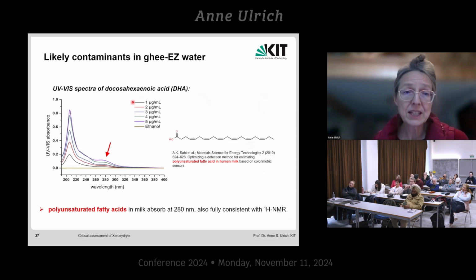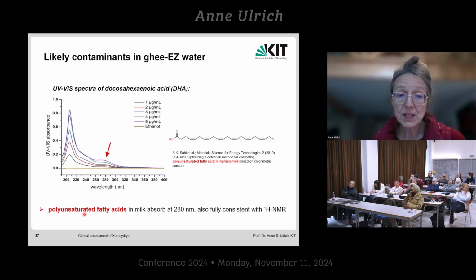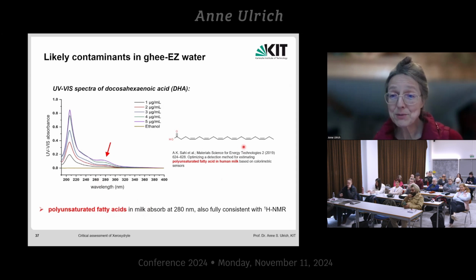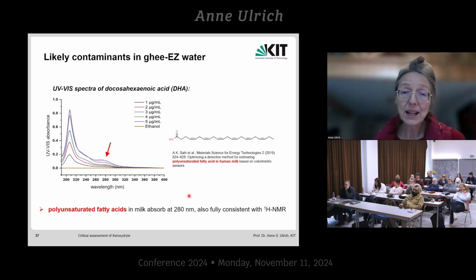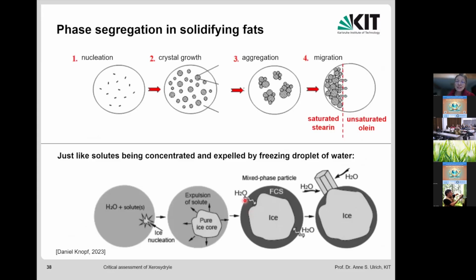And turning to the literature, it is in fact known that, for example, docosahexaenoic acid, which is shown here with lots of double bonds, has a pronounced absorbance at 270, 280 nanometers. And this polyunsaturated fatty acid is highly abundant in milk. It's very healthy for pregnant women to drink milk because of this DHA fatty acid, as was written in the paper of 2019. So this interpretation is fully consistent with our NMR data. And now let me try to explain how it comes that we enriched so much unsaturated lipids on the surface of the ghee sample.